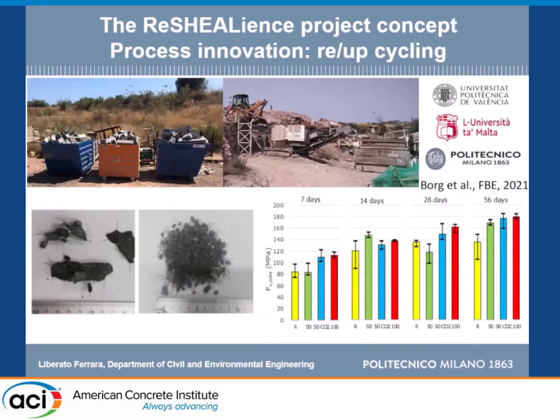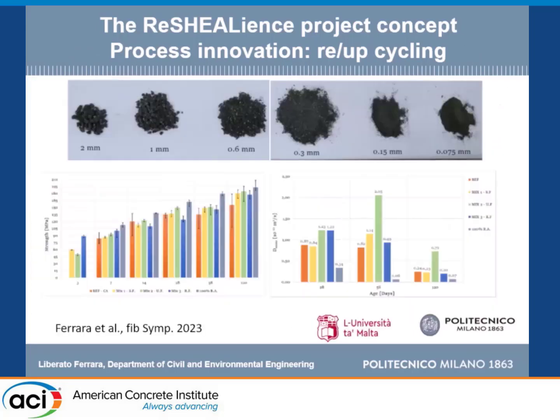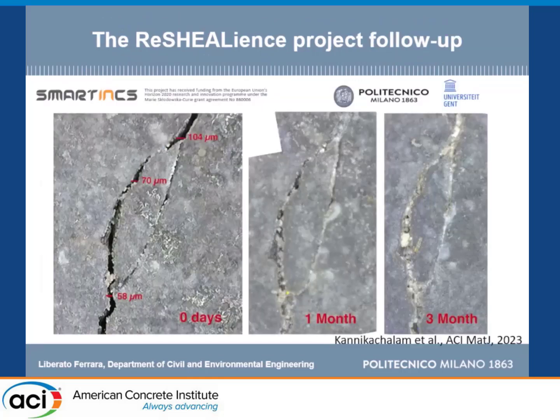So we try to address the recyclability of this material. And we demonstrated that you can keep the mechanical performance. This is the compressive strength. You can also use, with fine crushing, this material as a partial replacement of cement and not only of aggregate. And we kept the self-healing capacity of this material as well.